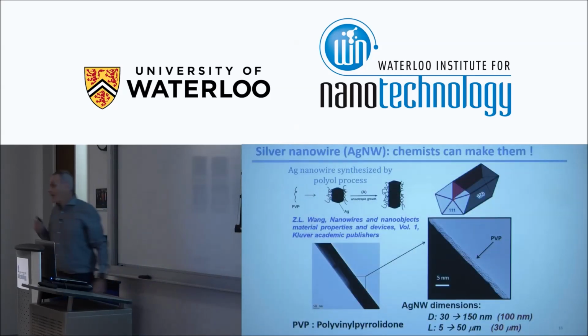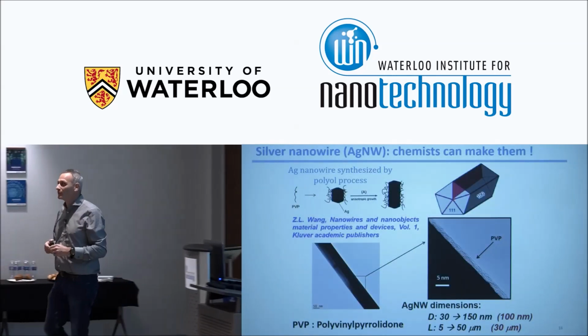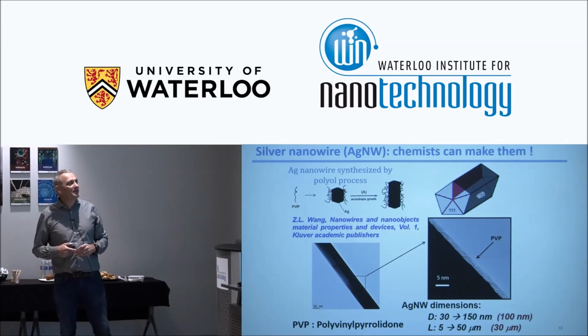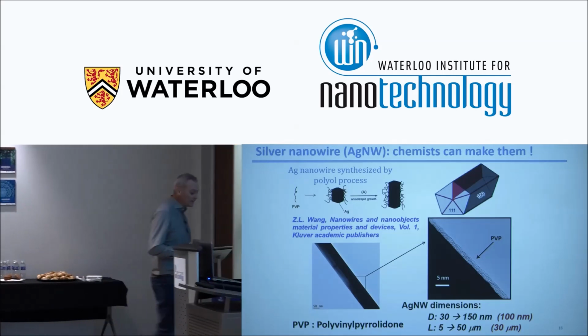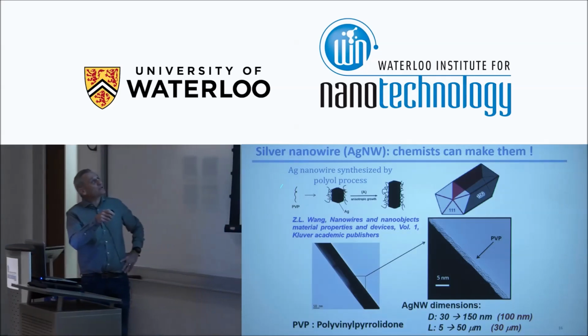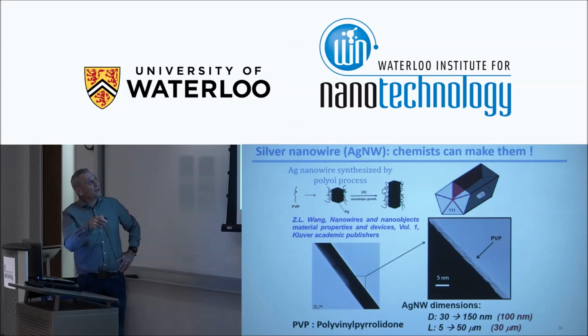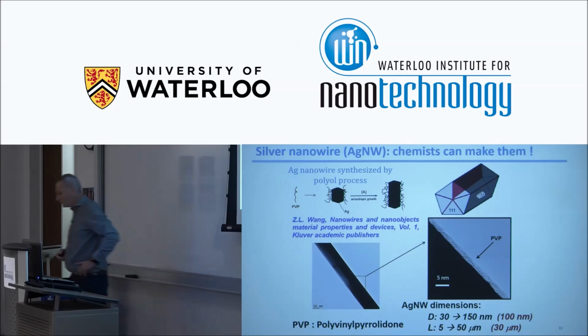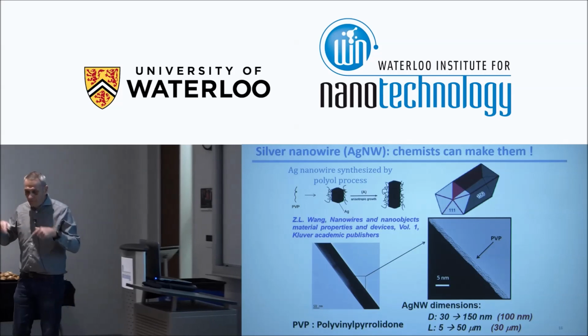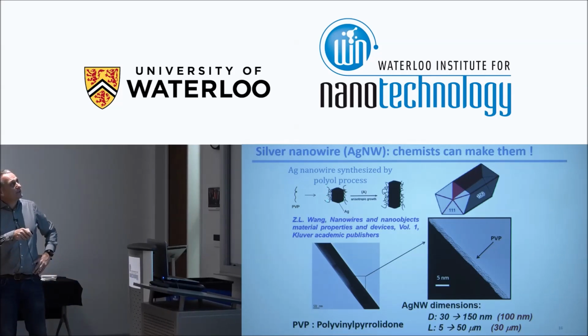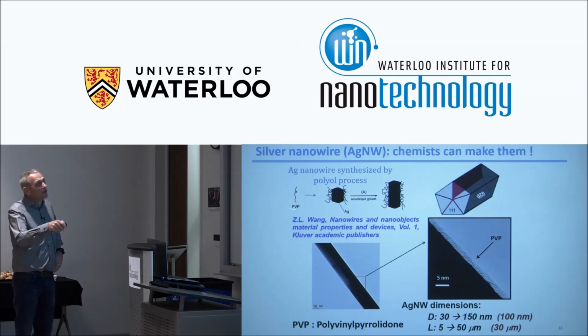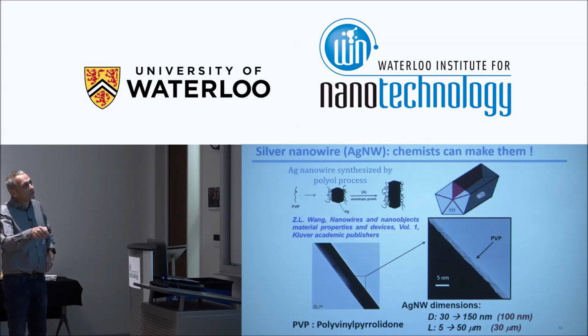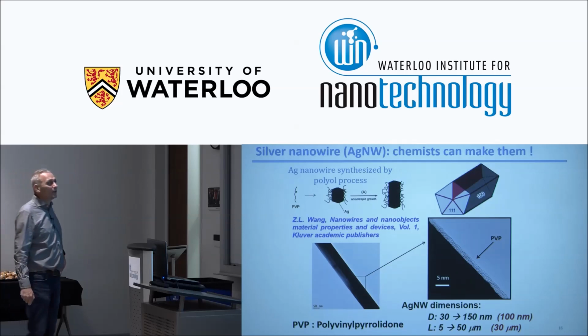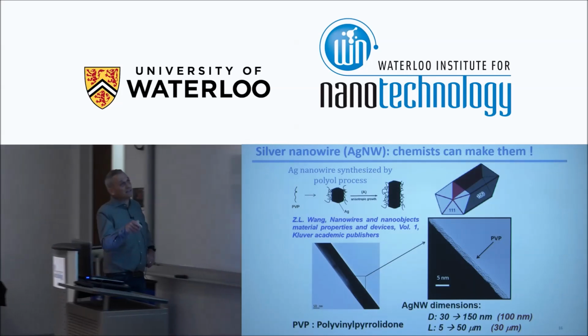So, I'm a physicist. I don't have a very good relationship with chemistry, but I interact with chemists, and chemists, they know how to make metallic nanowires. They use a polymer which is called PVP, for polyvinyl pyrrolidone, and they use some very small silver nanoparticles, which have some crystallographic facets. And this polymer PVP is going to adsorb preferentially on the 100 surfaces here, leaving free the 111 planes here. And this is where the growth is going to occur. There will be more silver atoms here and here, and this is why at the end we have a one-dimensional growth. Schematically, it's something like this.